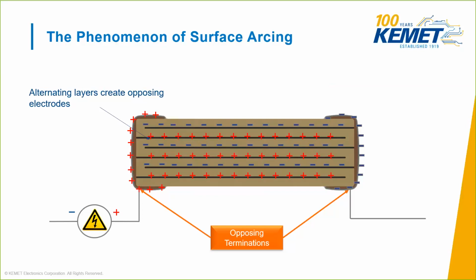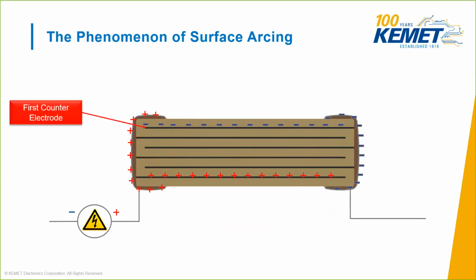As the voltage increases across the MLCC terminations, the magnitude of the electric field increases between the electrodes, and as the voltage is increased way beyond the rated voltage, the MLCC will eventually undergo a dielectric breakdown. For this slide, we've removed the positive and negative voltage symbols in the inner electrodes to really focus our attention on the outer electrodes of the MLCC.